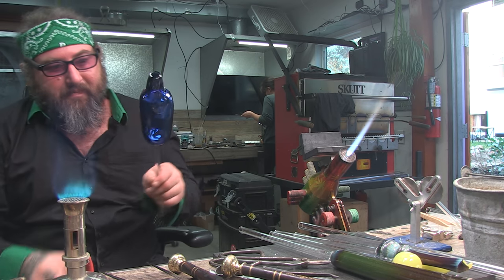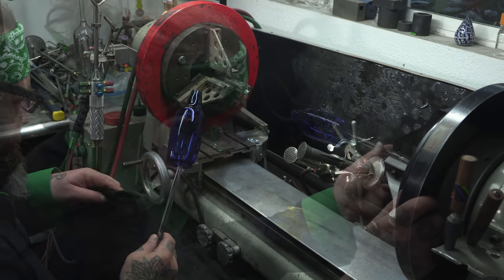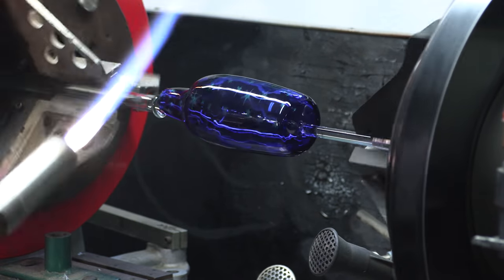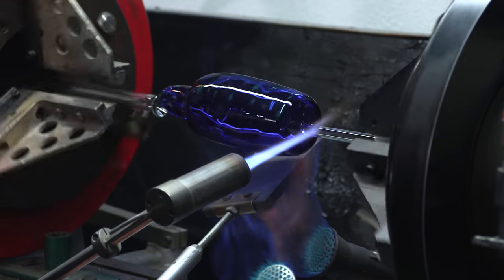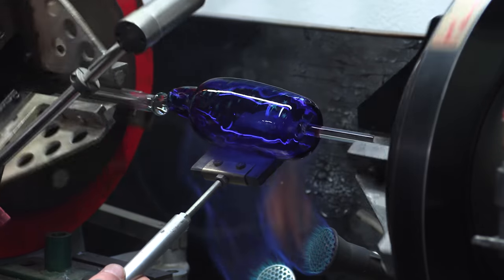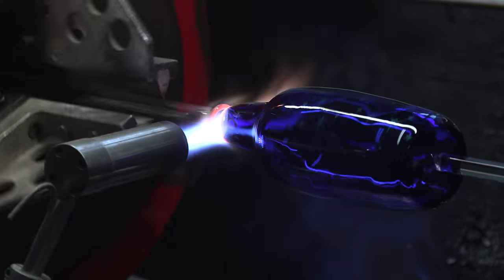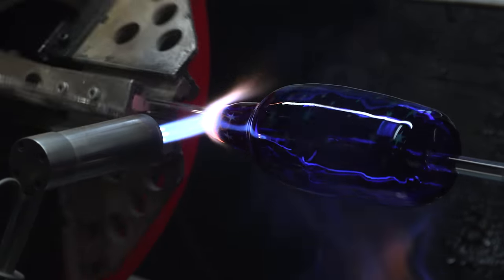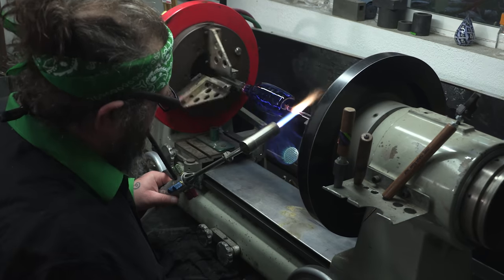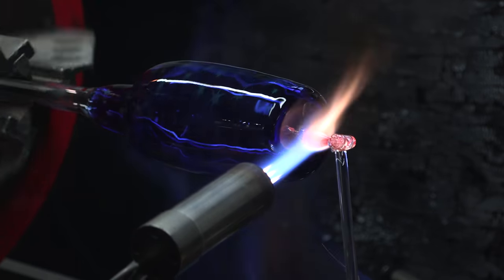Going back into the Bunsen, keeping this heated up, making sure that even after I fix the cracks I equalize the temperature a little bit and then put it in the kiln. Let that sit for maybe 15 to 20 minutes — let it all really come up to temperature. Now I'll pop it in the lathe and get back to business. Looks like I've got to straighten this out — it got off center with the Bunsen work. Putting it back in the lathe and sealing back up to the blow tube because I really want to make sure the bottom is smooth and that where that crack went over the edge is smooth. Going to put it back in the lathe and rework this a little bit to get it smoother. Under where that punty seal is, there's probably a little bit of variation — I want to reshape that whole bottom, and redo the punty attachment correctly so no more cracks generate from the punty.